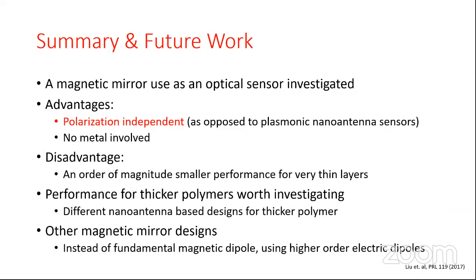So in summary, I tried to see if a magnetic mirror can be used as an optical sensor, and if so, what the advantage could be. It can be polarization independent, as opposed to plasmonic antenna sensors, which have to be polarized along the long edges of the rectangular nanobars. Otherwise, the signal enhancement will not be significant. And the other advantage is there's no metal involved for the magnetic mirrors, since it's all tellurium.